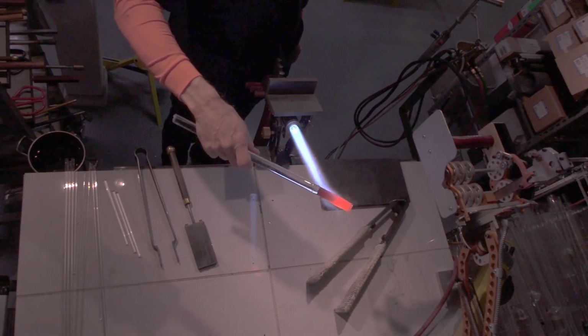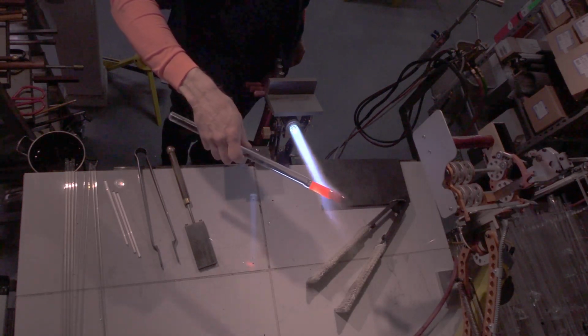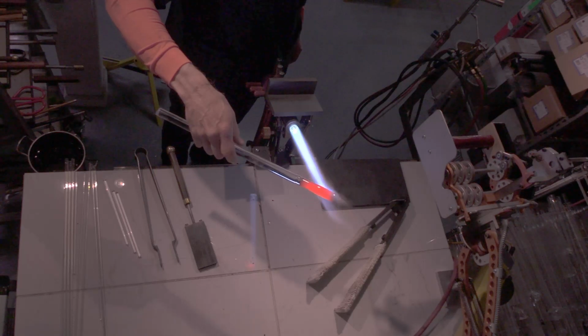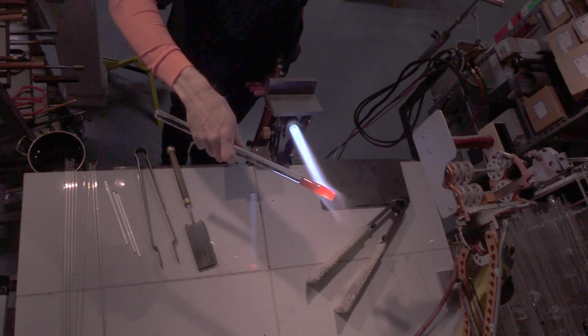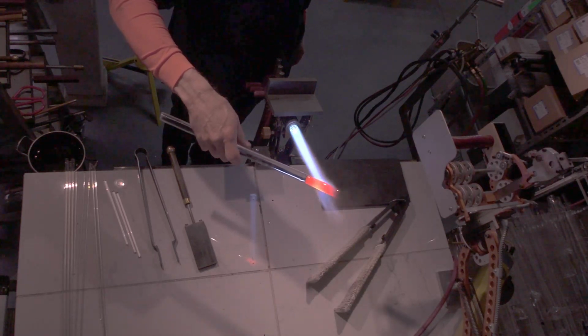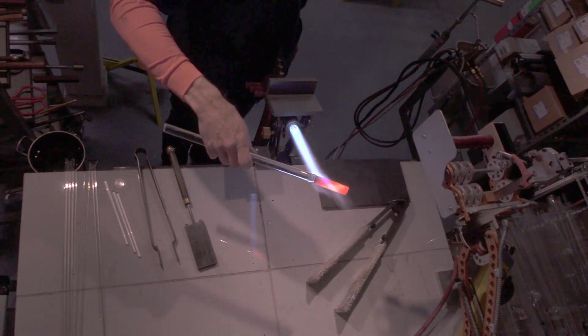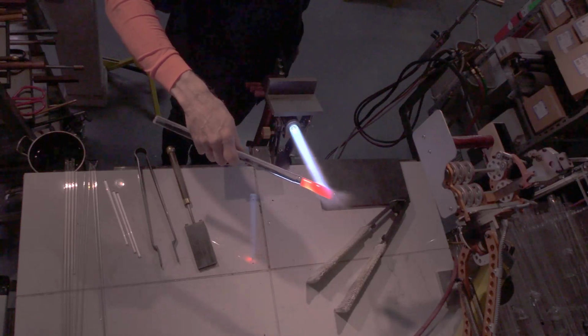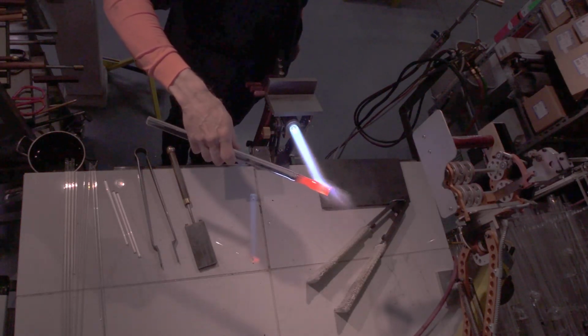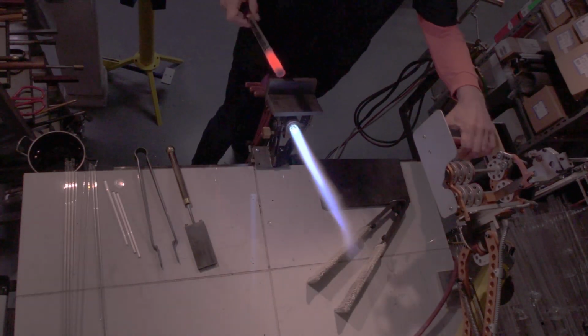Remembering that it takes a long time. Cold glass is an insulator, and it takes a really long time to soak heat into the core. Of course, heat travels much better through hot glass, which makes it a kind of nonlinear behavior that's rather difficult to comprehend, difficult to build an intuition for. So now the piece appears to be somewhat at working temperature,